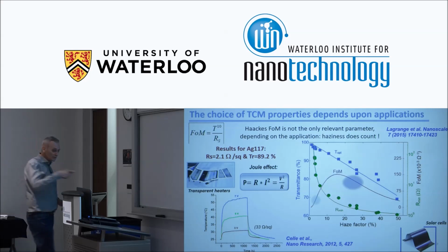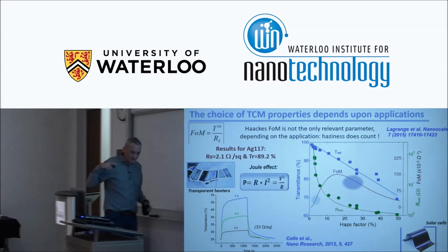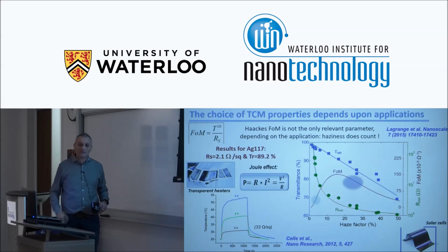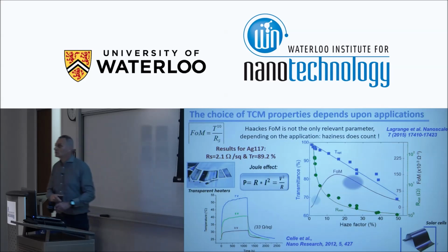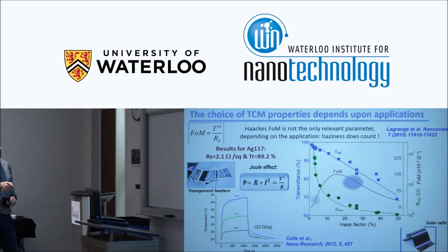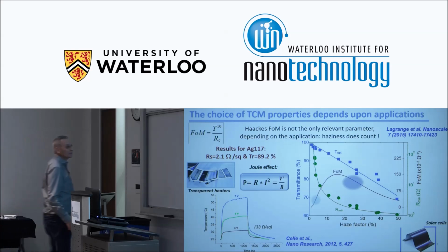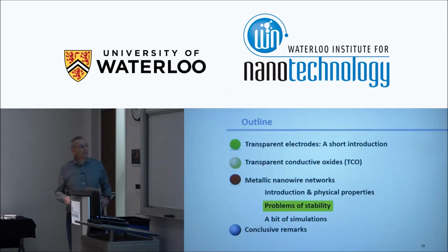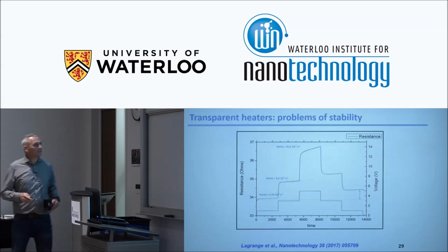And so with that transparent and conductive material, when the current density is crossing this transparent electrode, there is heating thanks to the Joule effect. And this is a way to make defrosting and defogging. And for sure, transparent heater temperature versus time, when we apply 3 volts or 5 volts or 7 volts, there's an increase of temperature. Okay, the first paper was coming from Jean-Pierre Simonato's team in Grenoble about 6 years ago. And that's pretty cool. And so for sure, we did some work on it as well.